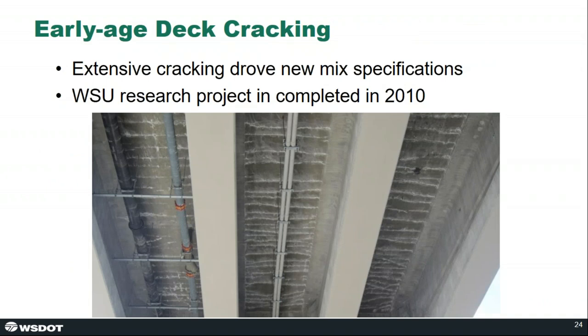So back to this issue of early age deck cracking. This was a problem nationwide, and the photo you see here is maybe one of the worst examples we've seen in the state. This bridge was open to service for just a few months before this sort of cracking was seen at a very tight spacing. Our dissatisfaction with this performance is what led us to a new mix specification, and Washington State University completed a research project with us in 2010 that led ultimately to where our current specifications are today.